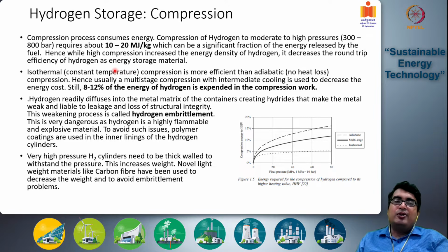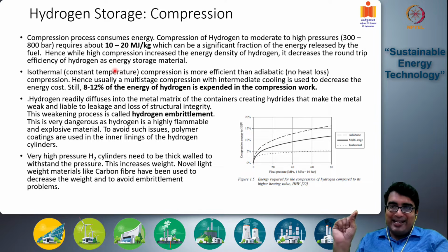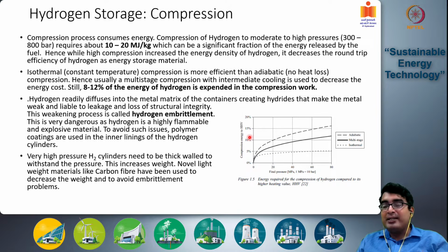In general, isothermal, that is constant temperature compression, is more efficient than adiabatic, that is no heat loss, compression processes. So if you see the two processes, this is the final pressure in megapascals. Now 1 megapascal is 10 bars, so 40 is 400 bars, 60 is 600 bars, 80 is 800 bars. And this is the compression energy as a percentage of the heating value of hydrogen. Alright, heating value is 120 megajoules per kg.